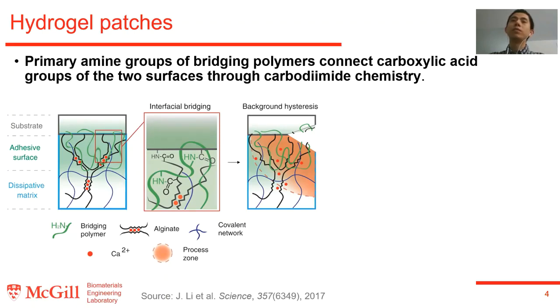To form covalent bonds, EDC and NHS can be used as the adhesive reagents. The amine groups can form covalent bonds with the carboxylic acid groups on the tissue surface under carbodiimide chemistry. To increase the bulk hysteresis, a double network hydrogel comprised of a covalent network and an ionic network can be used. This type of hydrogel is good at energy dissipation and is extremely tough.